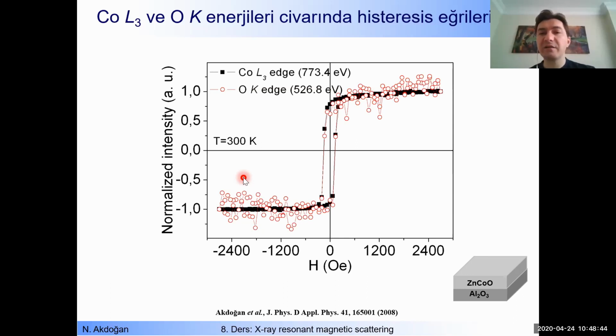What do you see here? The black one is taken for the cobalt. You see a very nice hysteresis curve. This is a very characteristic curve of a ferromagnetic material. And the red one, taken for the oxygen, also follows the behavior of the cobalt, right? It is noisy compared to the cobalt signal, but it follows. It has the same coercive fields, more or less the same remanence signals around here, and the shape of the curve is exactly the same as the curve taken for the cobalt.